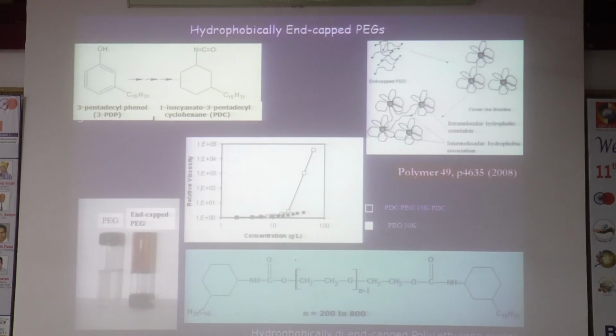So another example, third example is the polyethylene glycol. I mentioned to you about the flower-like micelles. So you can buy polyethylene glycol from the market, and polyethylene glycol, PEG, it has got 2 functional groups at the end, OH groups, and you can modify OH groups with this kind of a compound, and then you end up getting a polymer like this. It has got hydrophobe at both ends. When you put them in the water, they form micelle-like structures, and they show enormous exponential growth in the viscosity here, and you can see the phenomena happens here so nicely, and you can use these polymers for increasing the viscosity of your creams, wine, and solutions.